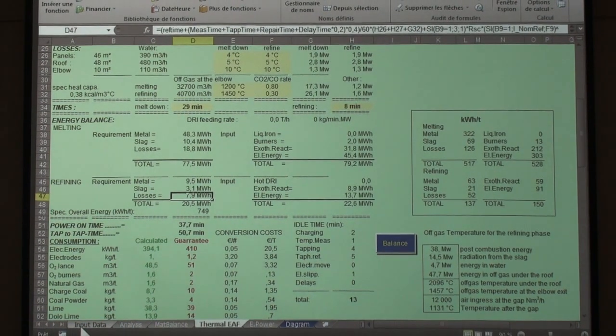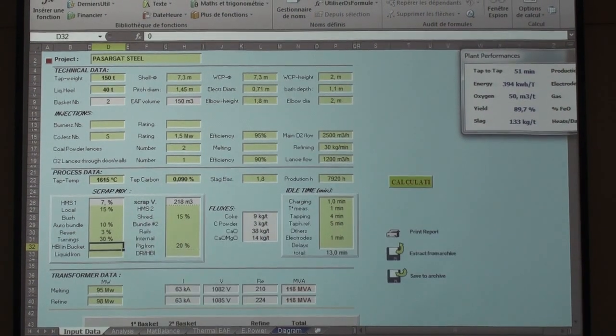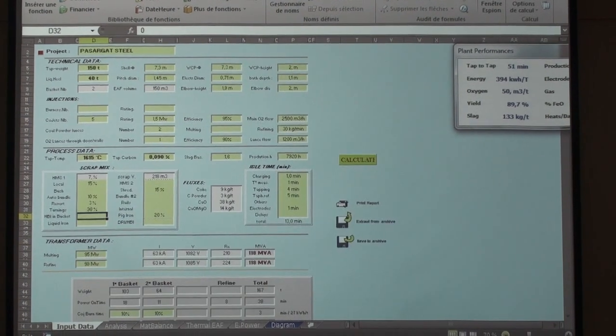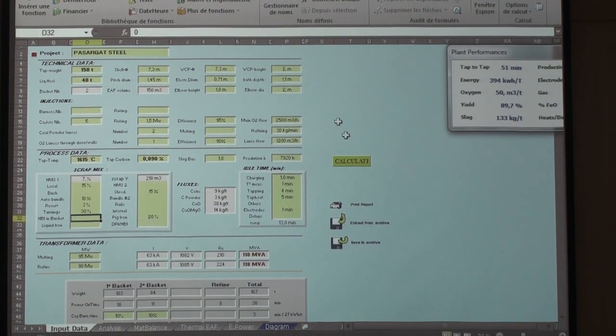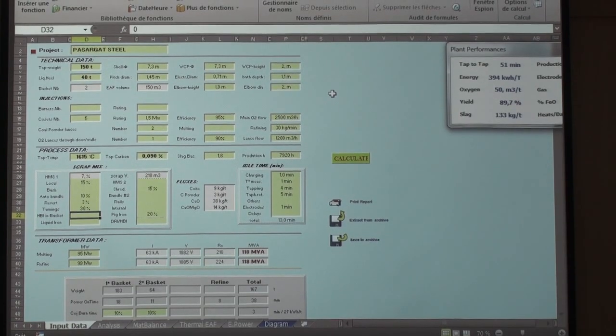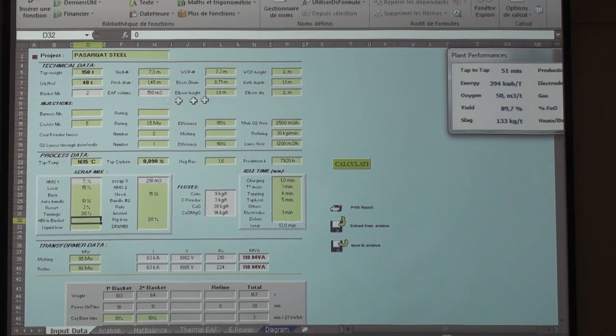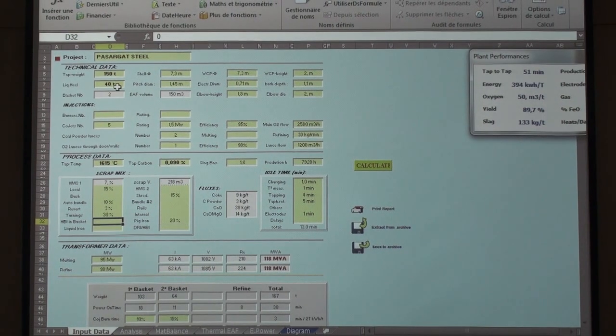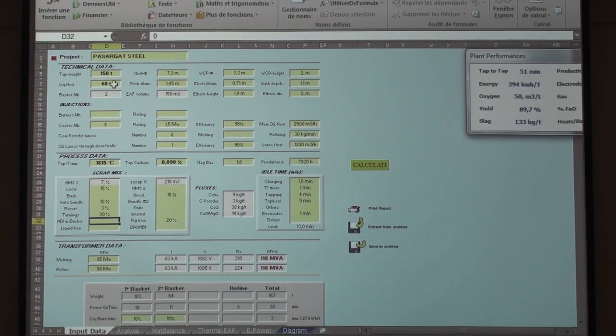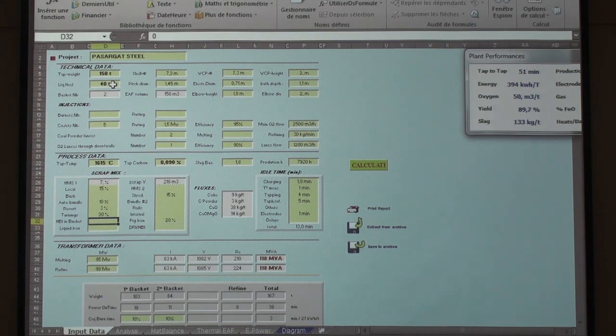Well, so if we come back again, when you have a project, the first thing to know is the tap weight. So you fill the tap weight and the hot heel. For a conventional furnace, hot heel is about 10%. Some other companies said 15%. Too high? Look, there were so many studies about how much hot heel you have to keep in the furnace. What is sure is that